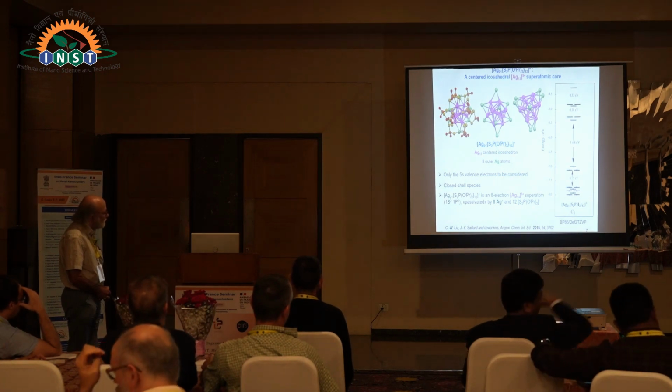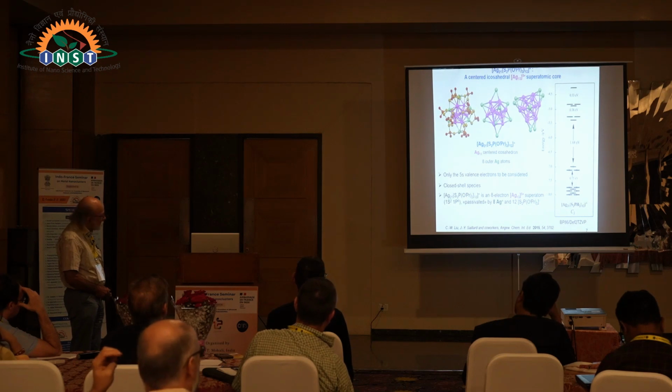And actually, we have a system which contains a superatomic core, silver 13 5+, 8 electrons, which is protected, or as people say, passivated, by 12 ligands, formally -1, and 8 silver 1. It's a closed shell.